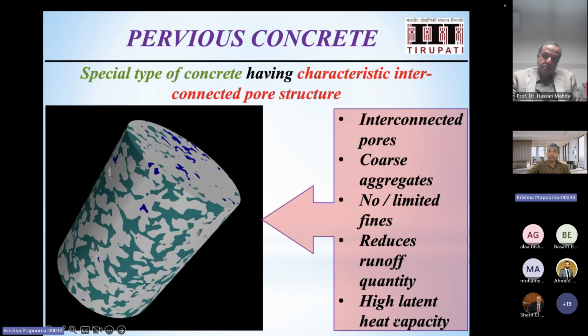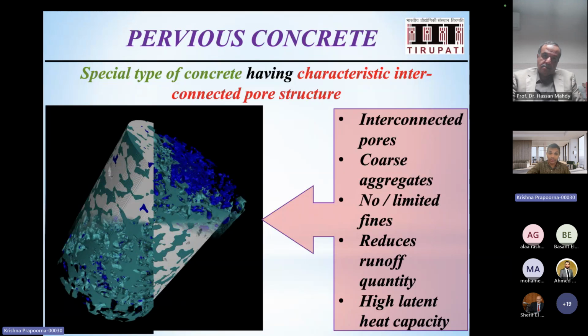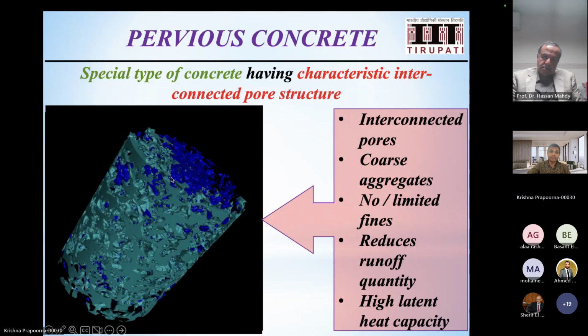So if you look at the interconnected pore structure using X-ray microtomography, this is how it looks. The top 25 to 30 millimeter in a 150 millimeter sample gets clogged because it has very high interconnected pore structure. So one of the major demerits of this kind of material is that it has very high porosity, which means it can get clogged. So that question always remains. So how do we mitigate that? That is another question that we have.